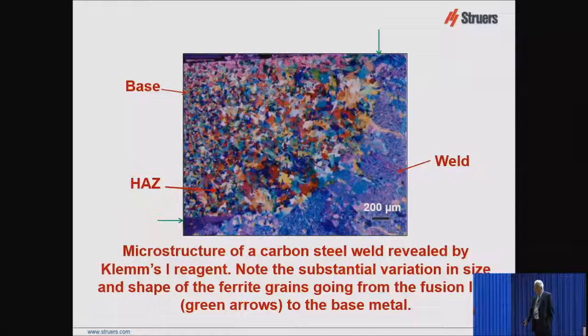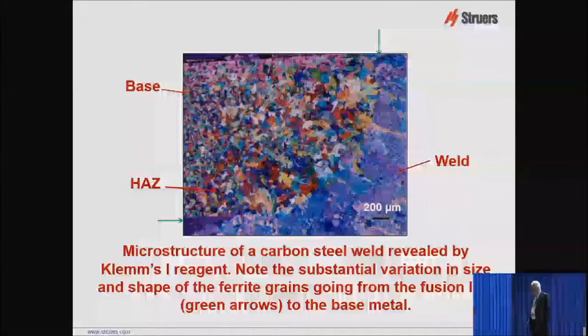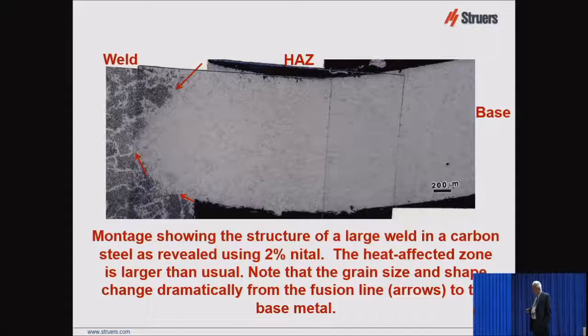This is all heat-affected zone. You can see as you move towards the fusion line here, that structure is getting somewhat coarser. Not vastly coarse, but coarser. Now, this example will be followed by the same exact area, but in color. And if this doesn't convince you that color etching is worthwhile, I'm a monkey's uncle.